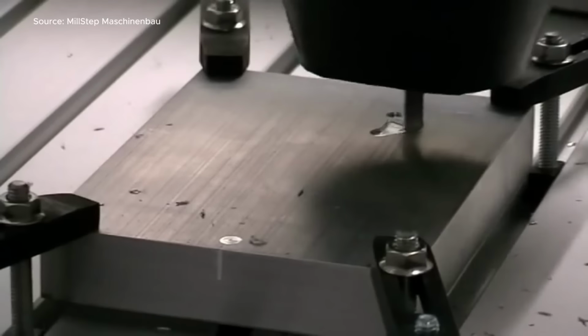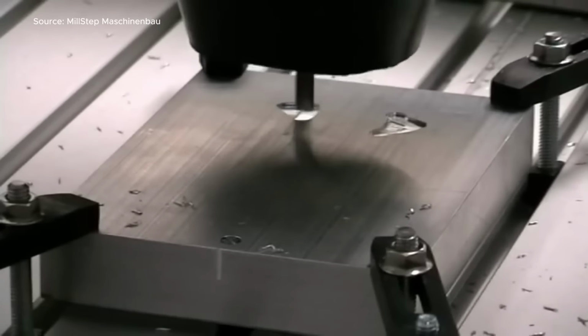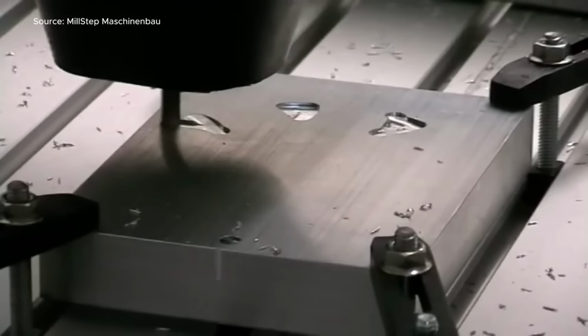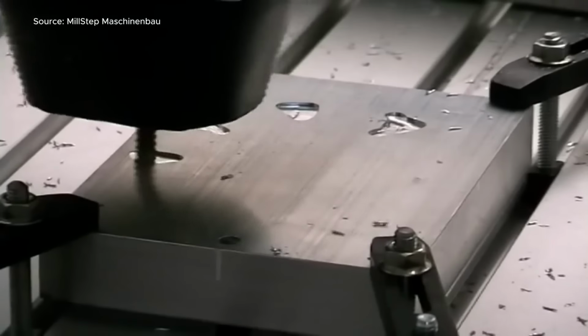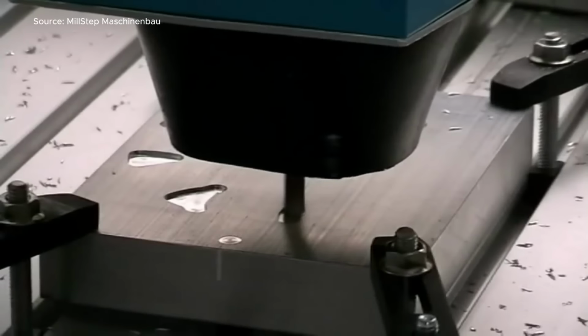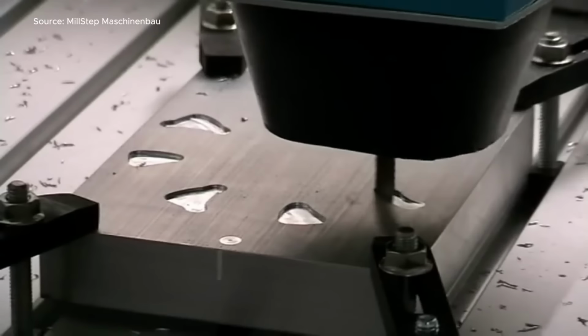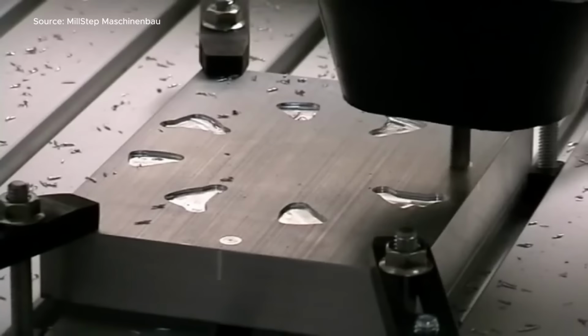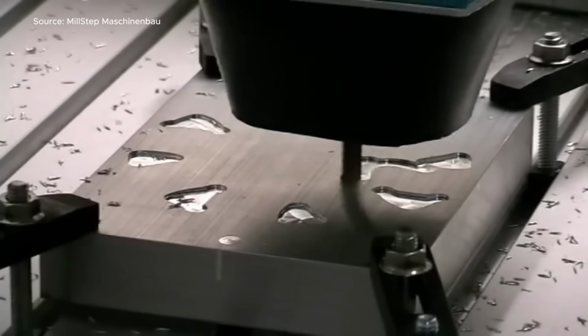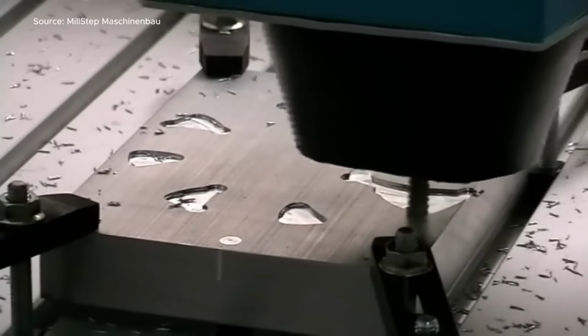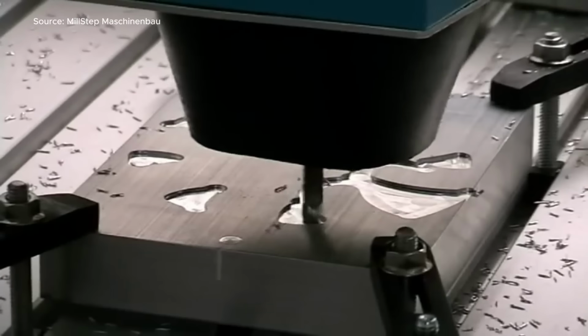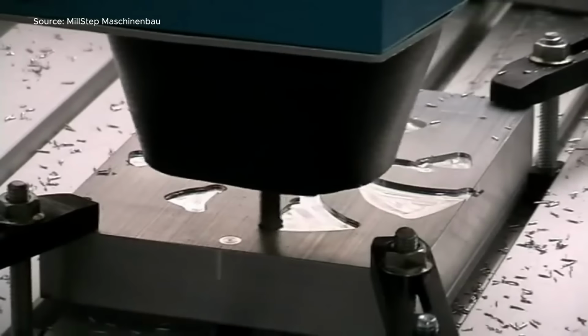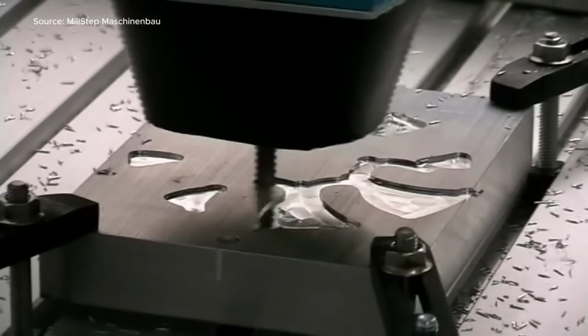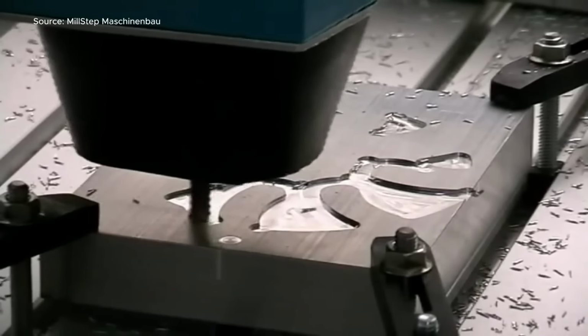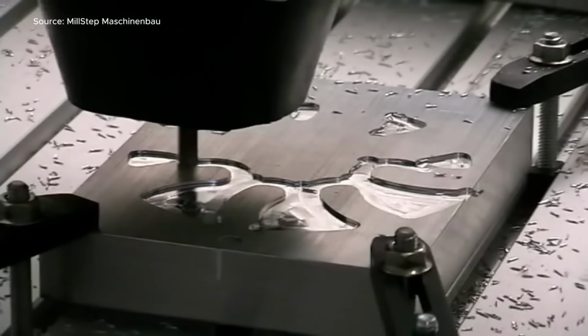It's incredible to see a block of aluminum precisely machined into a complex blower wheel using advanced CNC milling. The process starts with Z-level roughing, where a 6mm flat end mill cuts away large amounts of material in 0.8mm deep passes and a 4.8mm step over, advancing at 32mm per second. The tool carves out the main shape, leaving a rough outline that already hints at the final form.